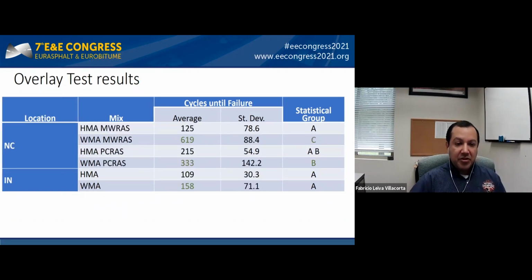For the other two projects, we found a couple of pairs where warm mix outperformed the hot mix. But in most cases, we found that that was not the case. For some of them, the variability didn't show as significant difference. But in a couple of cases, as denoted by letters C and B on the grouping, we were able to find that those were indeed different.